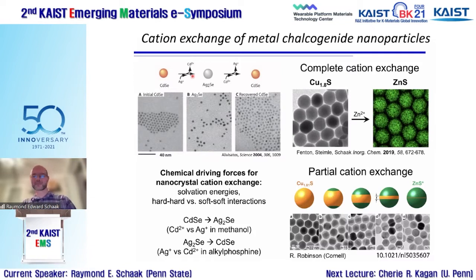Once you do a cation exchange reaction, as the Alivisatos group and many others showed, you can cycle it back by just switching the chemistry that's happening in solution, switching what the driving force is, switching what the reagents are. And so it really redefines nanoparticles as reagents, the idea that you can start thinking about nanoparticles as chemical reagents that could be modified and transformed into other products, other species.